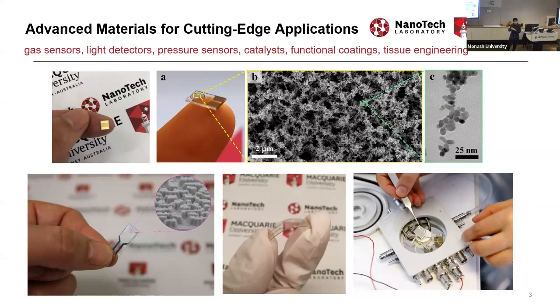You can control it, but sometimes we prefer that defect. It works in our favor. Again, for example, oxygen vacancy is one of the main defects we get in these films. Of course, if you want to minimize it, you can provide more oxygen.